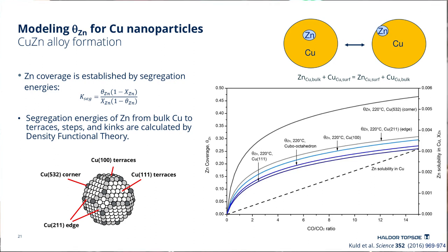So the segregation energies are converted into a zinc coverage on the abundant copper 111 terrace, which looks like this. Initially, it's growing quite fast, but then it seems to stabilize at higher reduction potentials. If you go to the more open copper 100 surface, it's slightly higher, but it seems to follow the same trend. And if you go to the edge sites, it's even higher, but again, it's following the same trend. And the very undercoordinated corner sites, this is where the zinc would really like to go initially, so it has a really high coverage.